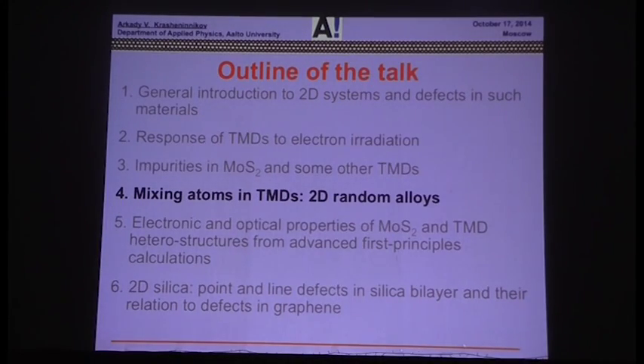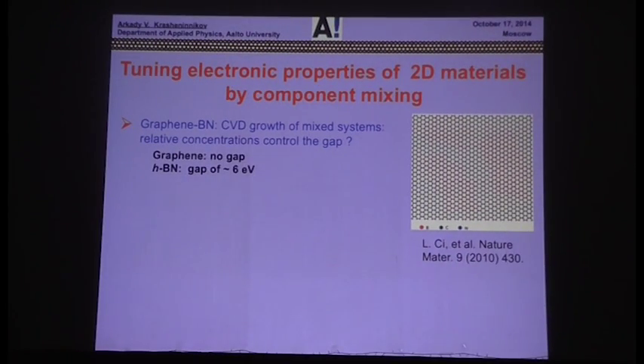Now, about mixing atoms. As we all know, graphene has no gap, boron nitride has a gap of about 6 eV. And the idea has been up in the air for quite some time to mix boron, nitrogen, carbon atoms and make a dream material with the value of the gap you want. Unfortunately, it doesn't work well because graphene and boron nitride tend to segregate. This is a cartoon showing basically small islands of boron nitride in graphene.